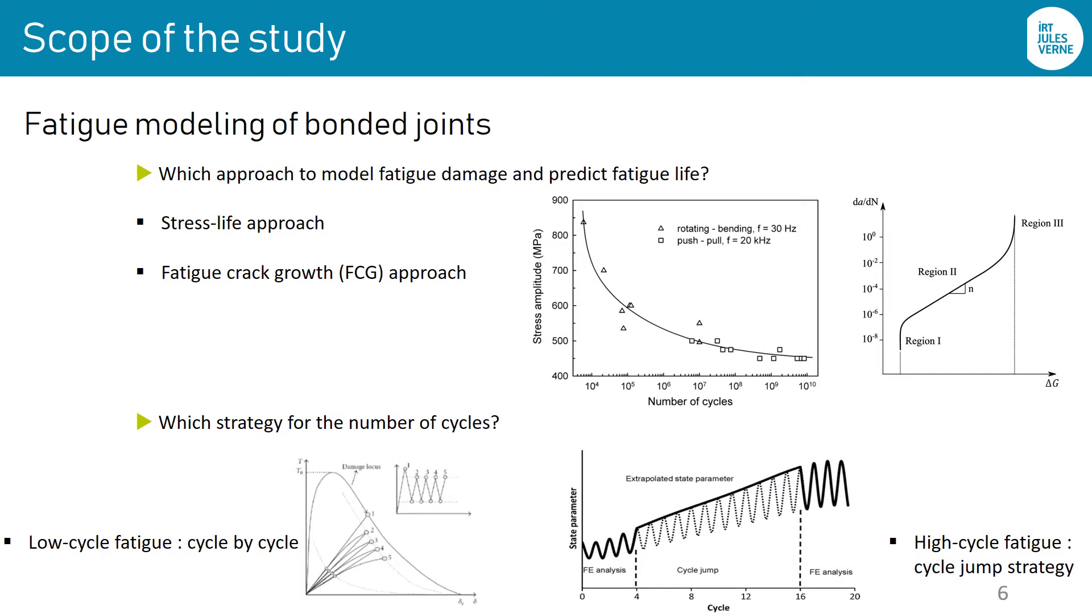Before starting fatigue analysis, some fundamental questions should be answered. Which approach to model damage and predict fatigue life? Stress approach characterized by the Wöhler curve, or a Paris law that gives the crack growth evolution with the stress intensity factor variation depending on the cycle number. The second question concerns the cycle number that can be taken into account for the analysis.